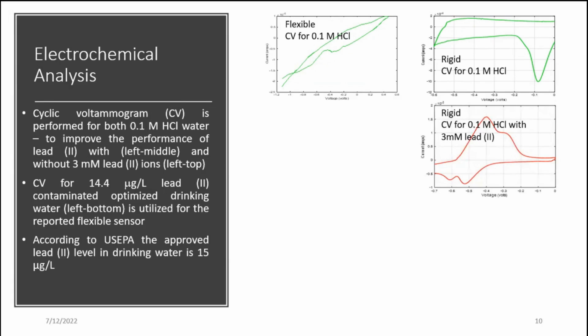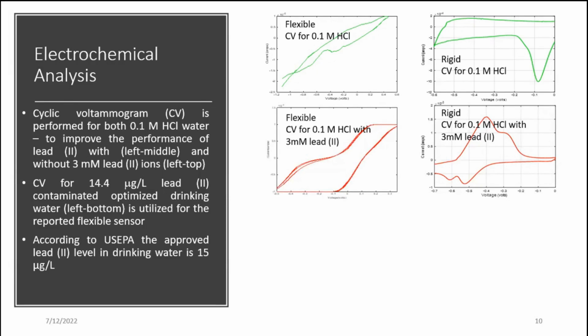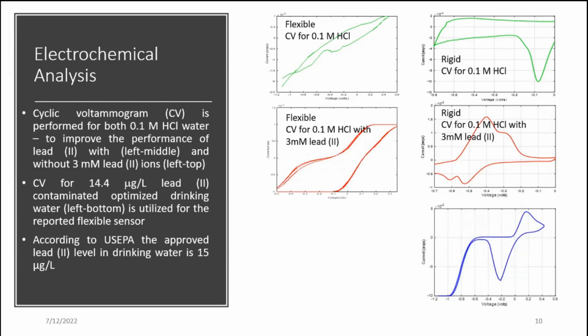So this is for rigid, for 0.1 molar hydrochloric acid with 3 millimole lead, where we can see some deposition and a stripping peak. But I will say from my analysis that due to some contamination, the peak is shifted a little bit to the left. This is for the flexible one for the same concentration. We can see some peak, but then again, in this region, we can see some flattened area where some information is missing. I'll talk about it in the next slide.